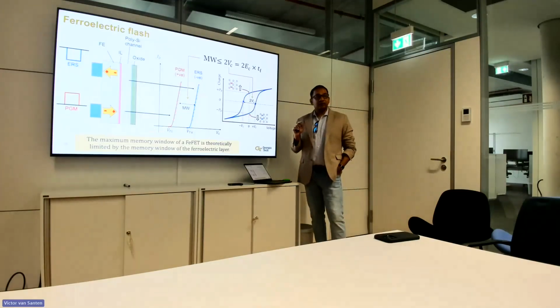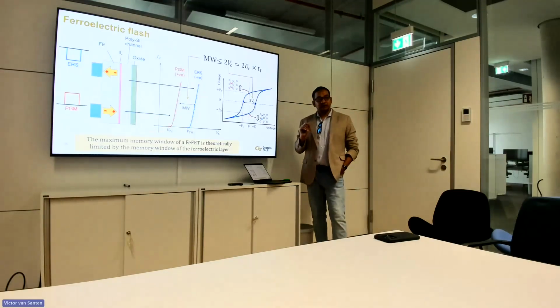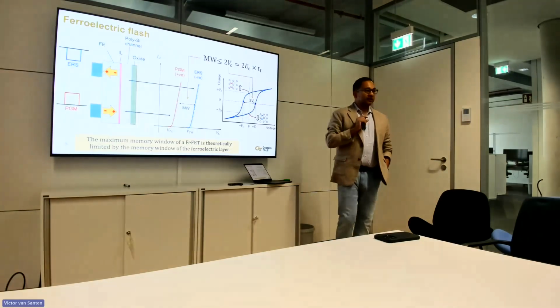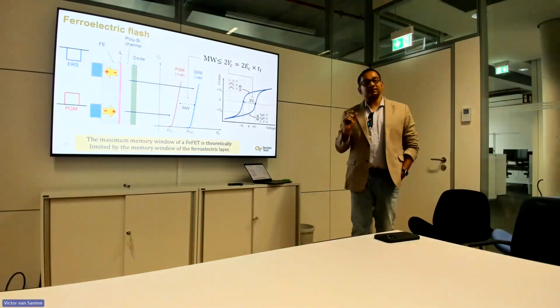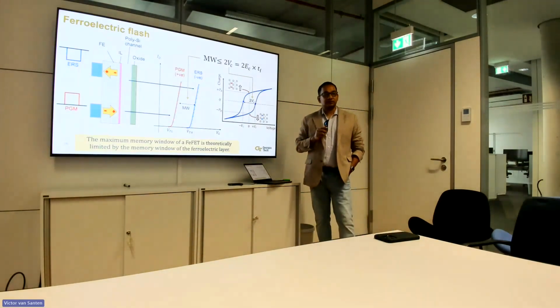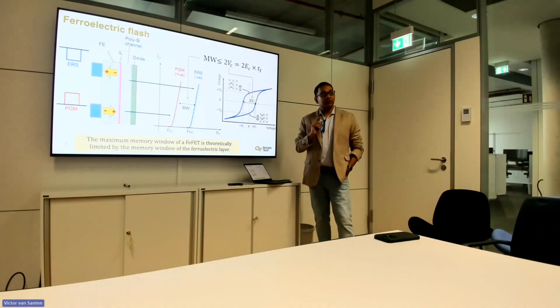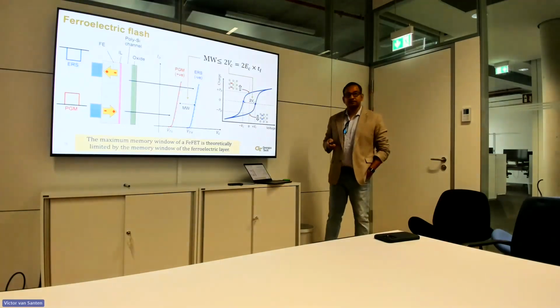Now, if you look at the coercive field of hafnium-based ferroelectrics, it's 1 megavolt per centimeter. So multiplied with 20 nanometers, you get 2 volts. So if you have 20 nanometers of ferroelectric thickness, you will actually at best get to 2 volts of memory window. Okay. So that's why it was not as straightforward to think about ferroelectric as a drop-in replacement for NAND flash.